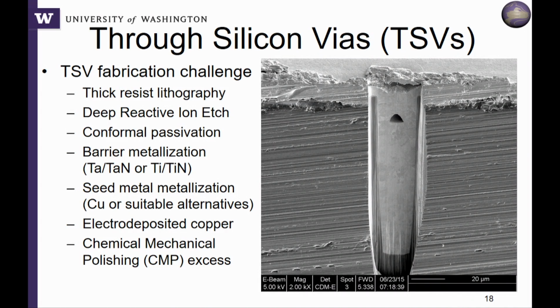After we cross those three hurdles, we then need to get a barrier metal down the hole, which helps prevent that metal migration through. Typically our industry uses tantalum, tantalum nitride, or titanium nitride as that barrier metal that prevents copper from migrating in. Then we have to coat it with a seed metal to get this hole ready for electroplating—typically we're using copper. Some of our advanced research at the lab works with other materials like cobalt and ruthenium, different things we can use to seed it.